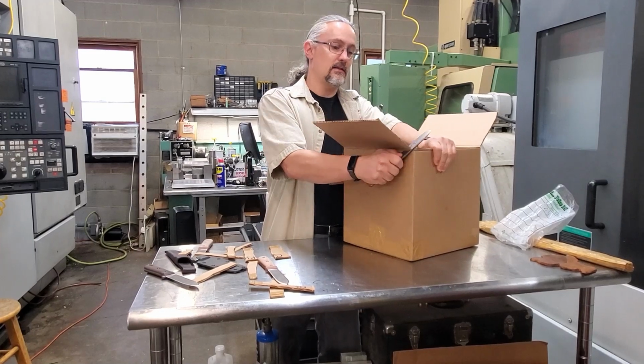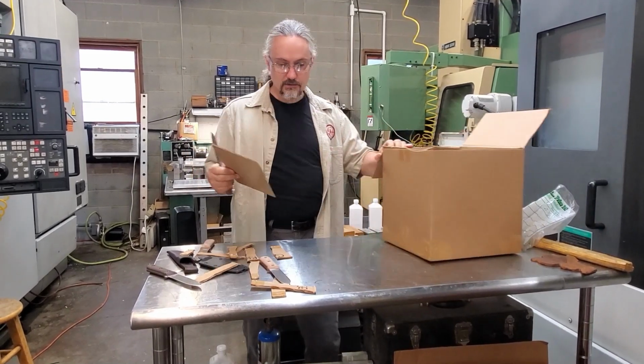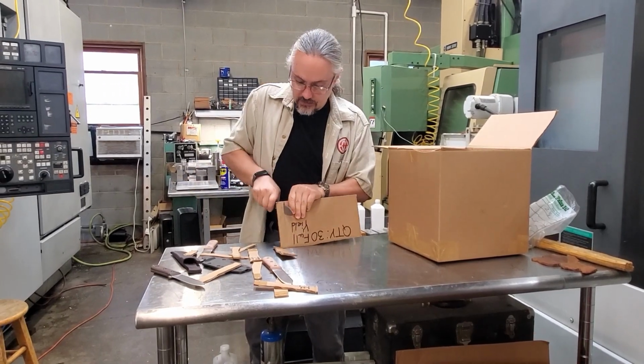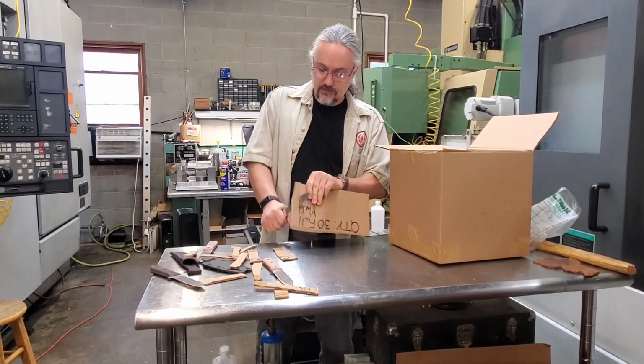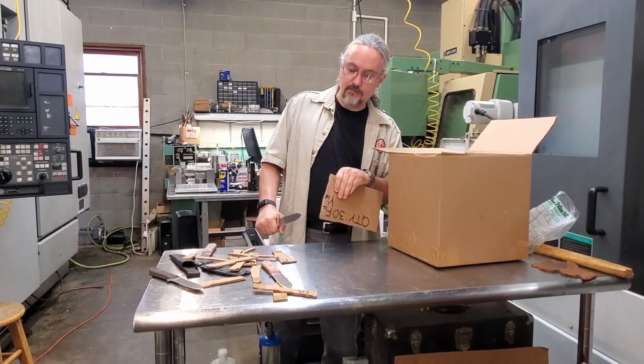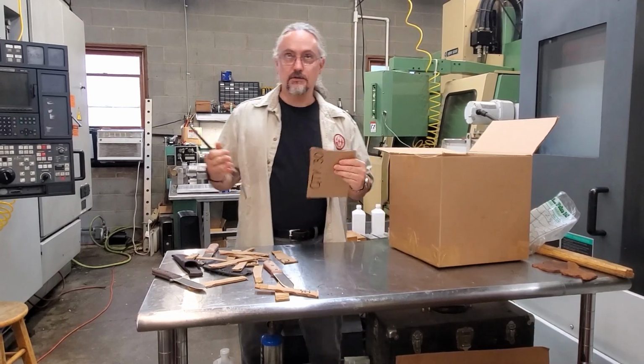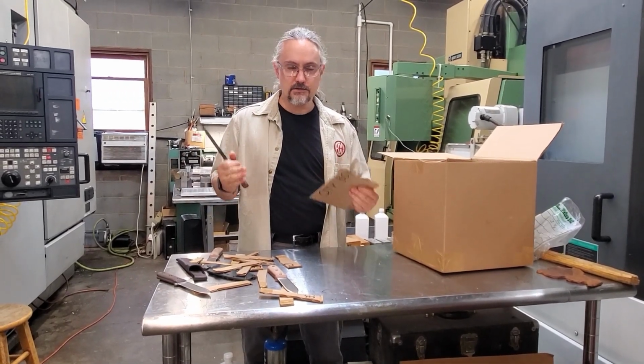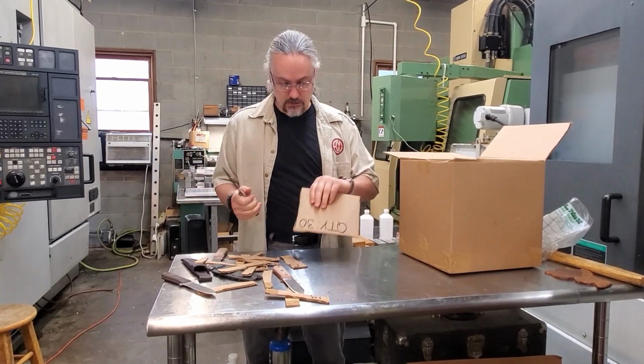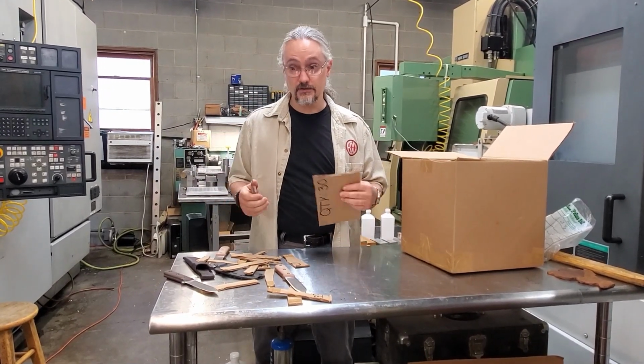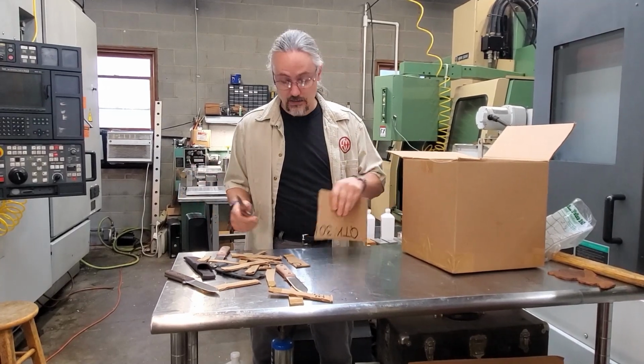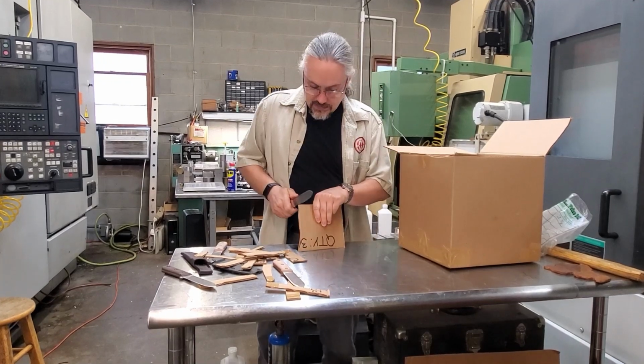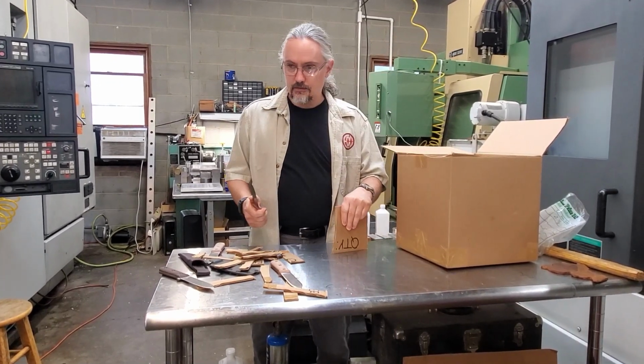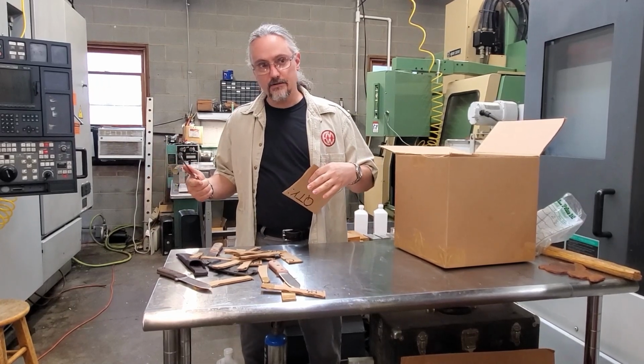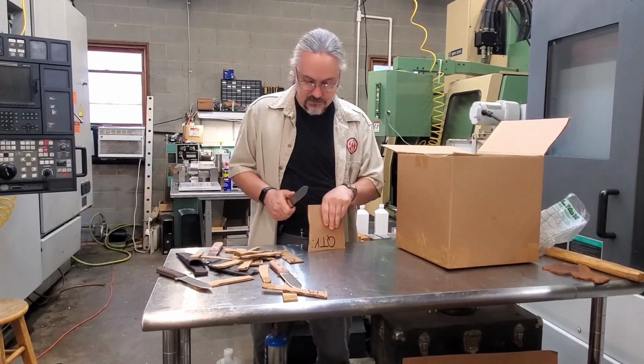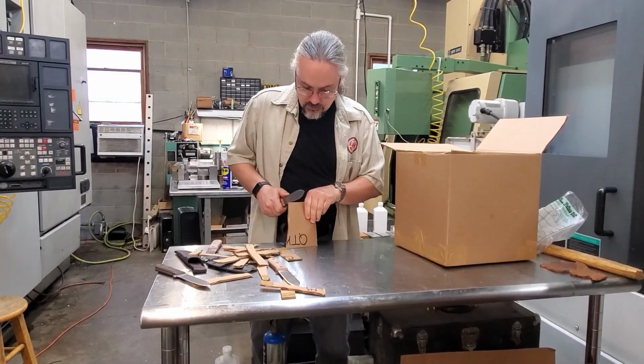And so you can imagine this hard structure, which we call martensite, is less dense once it's got all that jumble of carbon stuck between all of the atoms. That's a long way of saying that steel gets bigger after you harden it. Your tetragonal martensite is less dense. It takes up more space. And so the problem for people making tools and dies is their work is physically larger after they pull it out of heat treat, and so there are tool and die steels that are designed to minimize part growth, and they do this through a couple of ways.